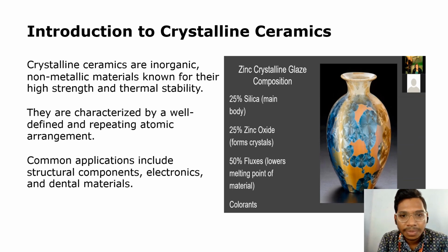Zinc crystalline glaze composition: 25% silica, 25% zinc oxide to form crystals, and 50% flux, which are lower melting materials.